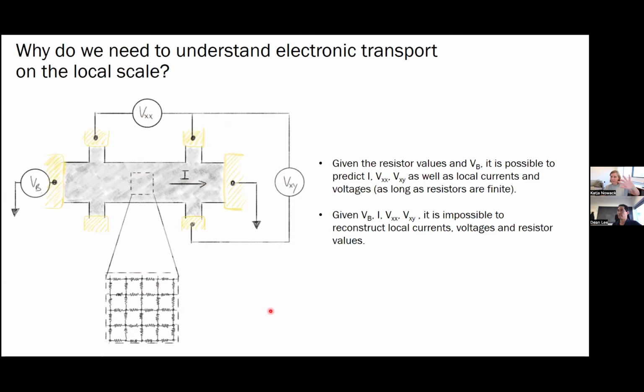And so the piece that I want to draw attention to is what we actually do when we do this transport measurement in the lab: we typically just assume that all these resistors are the same. So when we do a transport measurement in the lab, we very often interpret it under the assumption that the underlying material is extremely uniform. And it turns out oftentimes, especially when you work on new materials, that's not a good assumption.